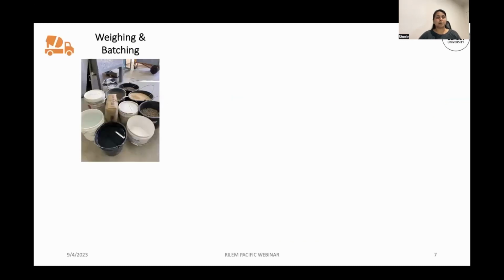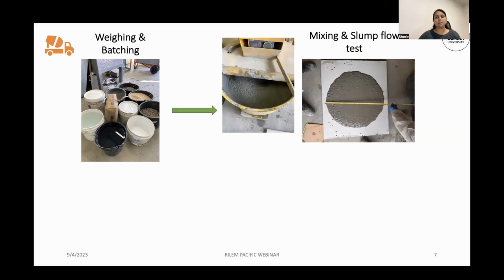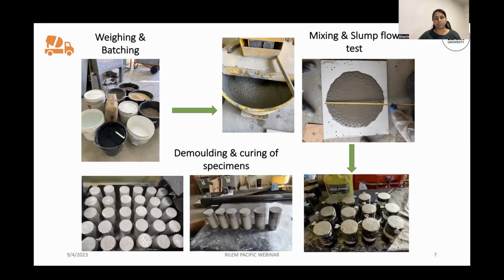This is a pictorial representation of the whole production process of geopolymer concrete specimens. We initially do the weighing and batching, wherein we weigh the materials that are required for the geopolymer concrete mix, and then we put them in the pan mixer. And we also do a slump flow test, which determines the flowability requirements and thereby the workability of the concrete. Finally, we cast the concrete, and then we demold the specimens after 28 days of curing. And in this, the curing is not underwater, it is directly air curing or ambient curing, where the specimens can be demolded and left as is in the normal environmental conditions.